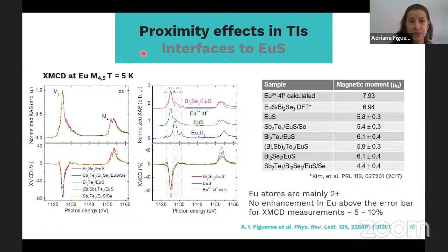So we first studied what happens at the europium site. We measured a series of samples of different TIs interfaced with the europium sulfide. We measured at the europium M4,5 edges, and we see that the europium atoms at this layer are mainly 2+.